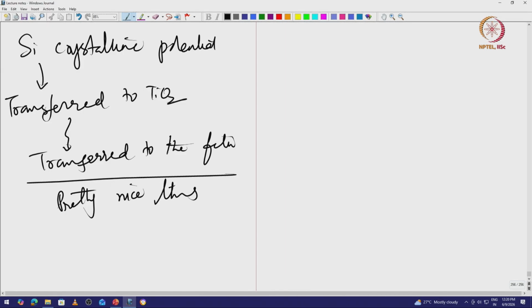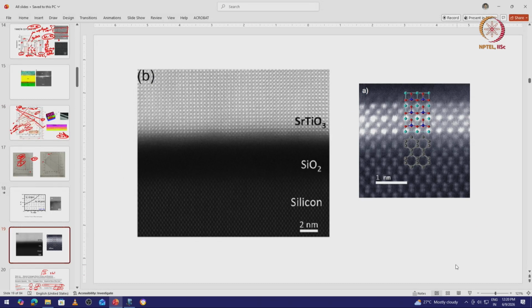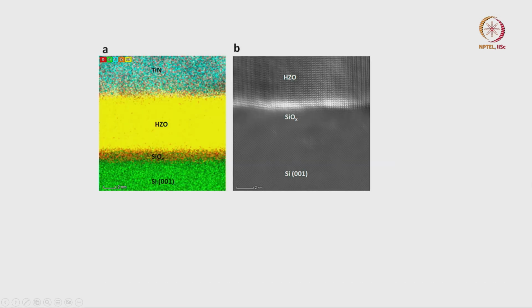Okay. So, in fact, you can see that this works, right. So, I will just show you quick examples, before solving a problem. So, do I have something here? Yes. So, for example, look, this is silicon, right, and then we put in some zirconium and hafnium. I mean, zirconium is more reactive than hafnium. So, ideally, this zirconium scavenged off silicon, right, and then gave a crystalline template of zirconium oxide, and then on the top of it we grew hafnium zirconium oxide on silicon, right, and you can see that this hafnium zirconium oxide is single crystalline.